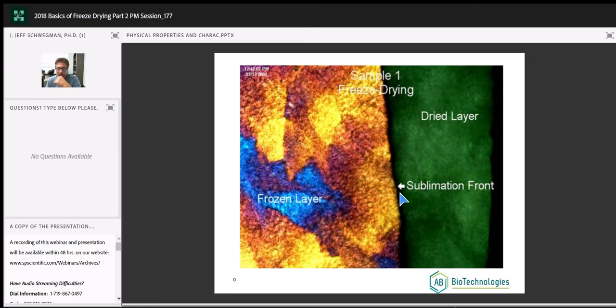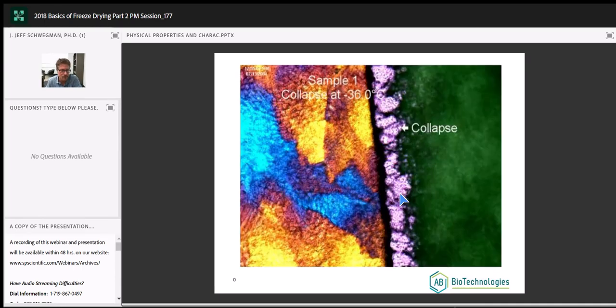It's a razor-thin line between the frozen layer and the dried layer where active sublimation is occurring. Once we collect this image, we then start warming the sample up and collecting images. We want to force this into a state of collapse so we know what temperature it goes through that collapsing event. Okay, boom. So we're back here. We're warming. We finally hit a temperature that exceeds the glass transition temperature. And like I mentioned, once we exceed the glass transition temperature, the interstitial space becomes a fluid. Sample can't support its own weight, and we get collapse. Now, you'll notice the frozen layer is still intact, because there's still ice in there that's providing scaffolding for the sample.